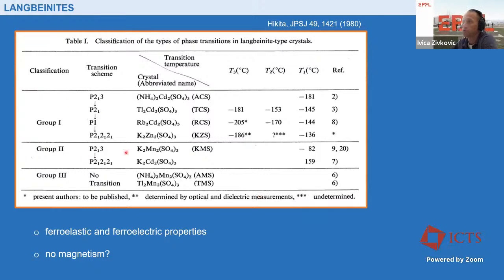And as you can see, some of them go through a series of structural transitions. And most of these transitions occur at relatively high temperatures, enough that they can be investigated with liquid nitrogen. So not much actually has been done at low temperatures. It has been either considered that there are no interactions, so it just behaves as a paramagnet, because maybe there were no shared oxygens between the metal ions, so it was considered that the interaction is too weak. Anyway, no detailed investigations of magnetism on this family can be found.